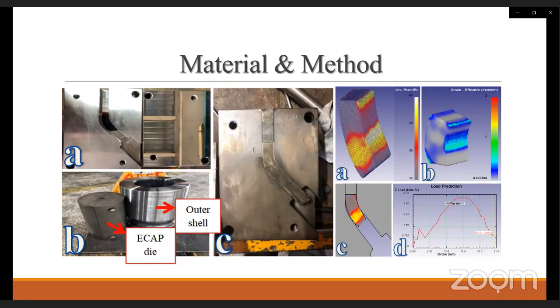But first of all, the surface quality is very important for ECAP. Therefore, the surface where the material is going to be touched is carefully polished before the operation, as indicated on the top left photo. It's like a mirror image. The ECAP die is subjected to heat treatment to obtain required hardness. Another important point for the ECAP die is the friction of the surface. In order to minimize the friction, we have applied nitriding heat treatment. The surface hardness is obtained with 62 HRC.